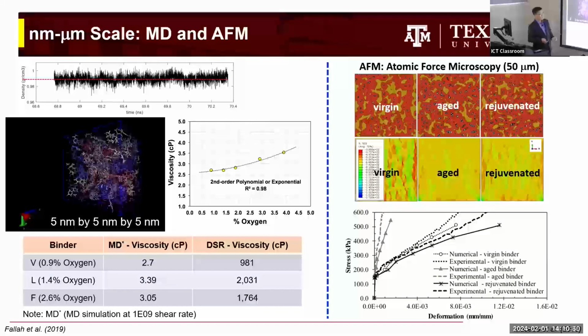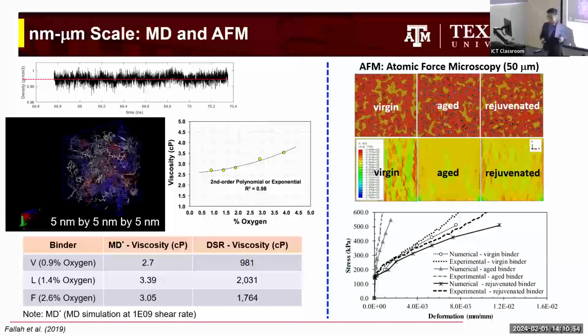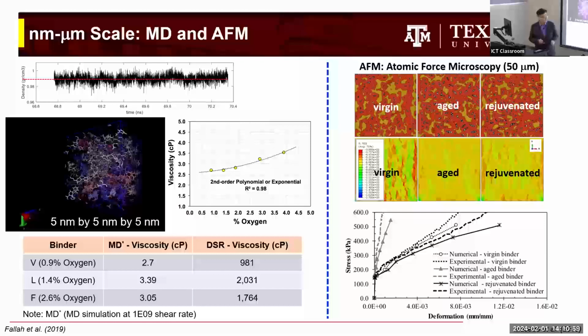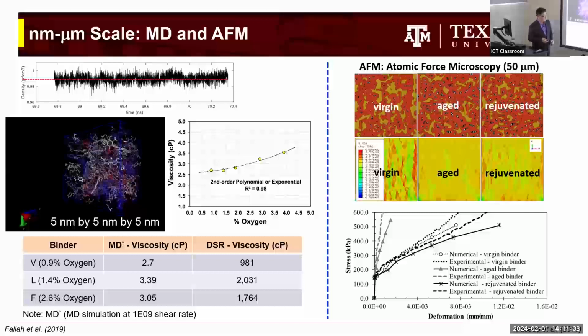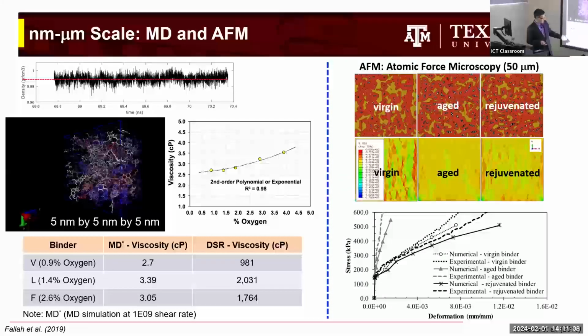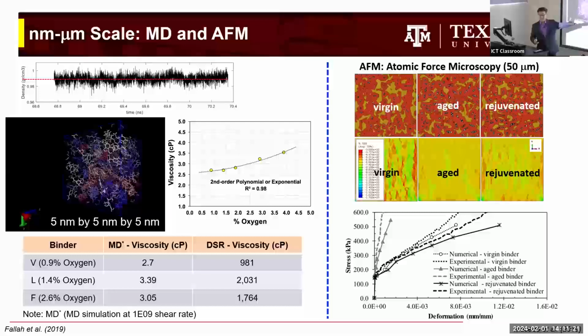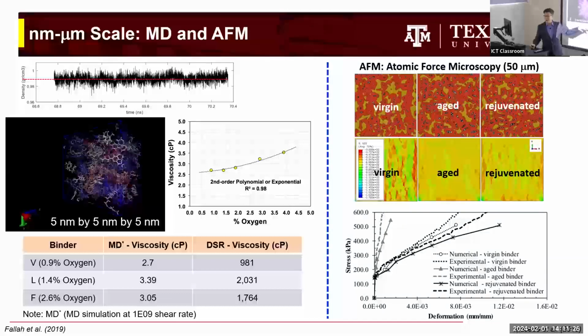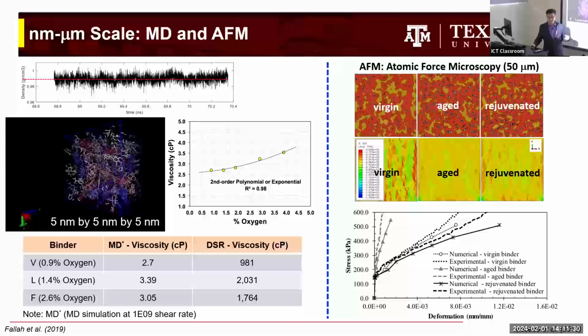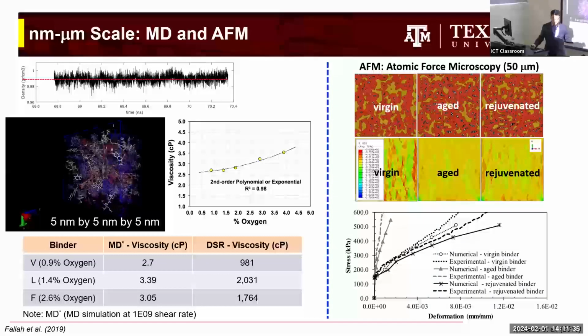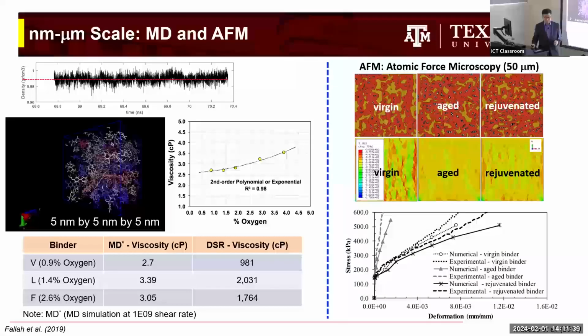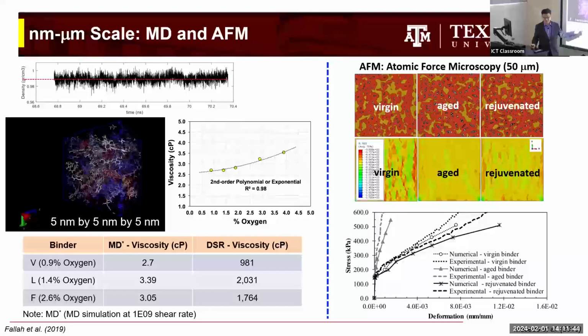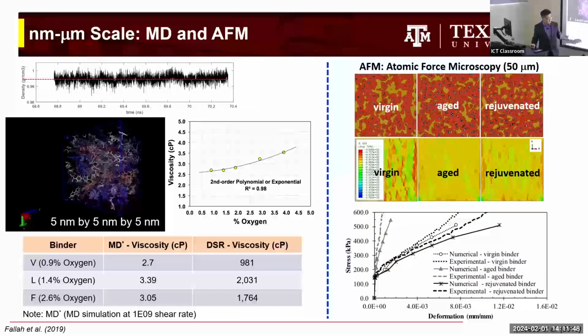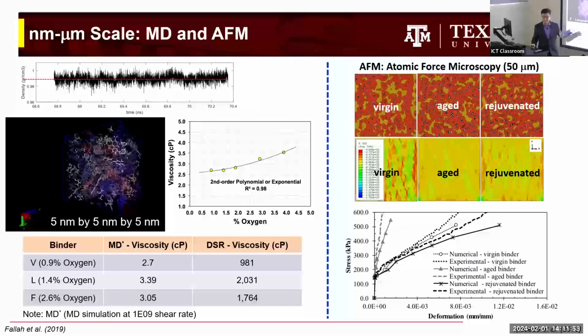Regarding the molecular level, which is not my area, I'm not a molecular dynamics guy, but one of my previous graduates was super interested in that. He tried to model at the MD level aged binder: virgin binder, laboratory aged binder, and field aged binder, and then did MD simulation for viscosity prediction. Then he compared with millimeter scale DSR, and you can see a huge mismatch, although we have a pretty good rank order match. So we found out MD is a different world. Because of different time scales, mostly, nanosecond scale versus second scale, we have a huge mismatch because the rate of shearing is very different. But that was the finding we got.